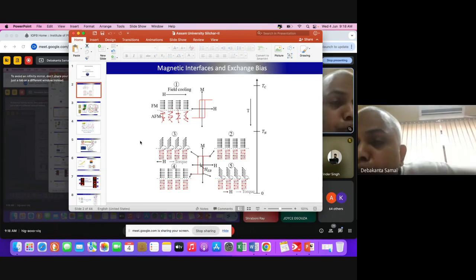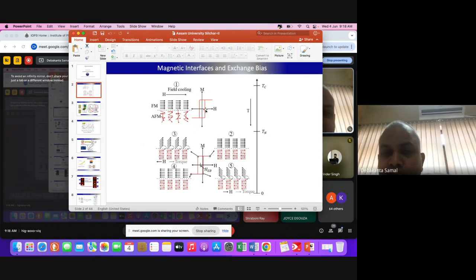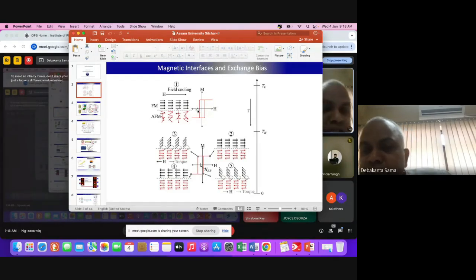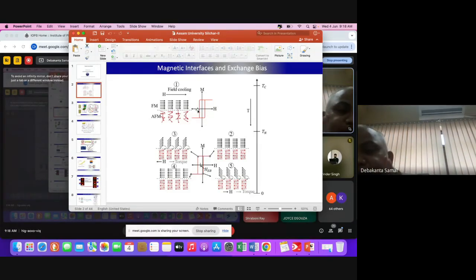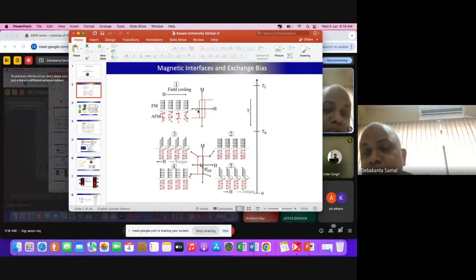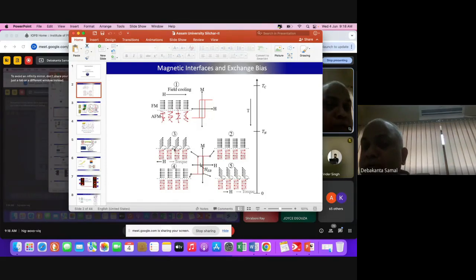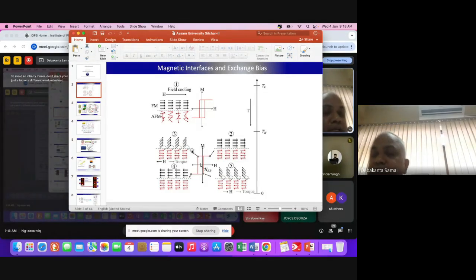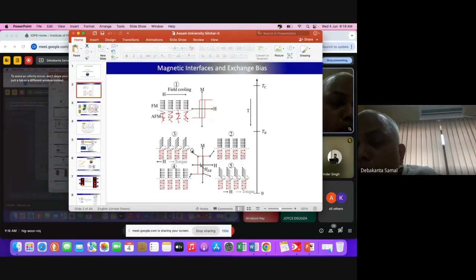Had it been a simple ferromagnet, look at the first top hysteresis: the positive coercivity and the negative coercivity are the same. But when you make such a measurement on a ferromagnetic system coupled to an antiferromagnetic system, what happens? Because there is some interfacial interaction, the antiferromagnet is interacting with the ferromagnet at the interface. So the ferromagnetic spins are not freely moving with the magnetic field; rather, they experience a kind of torque. What does it mean? You require more field in the negative direction to switch the ferromagnetic spins.